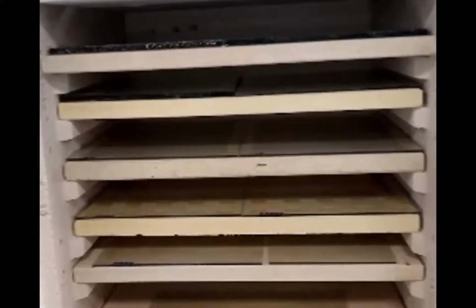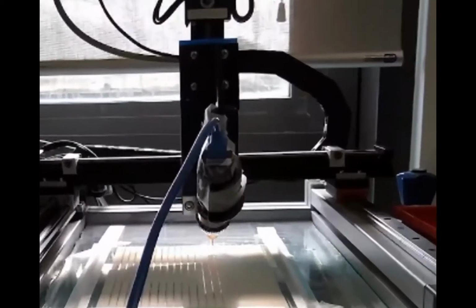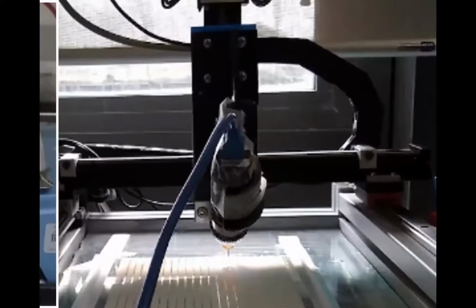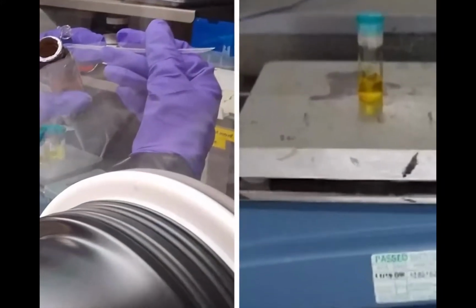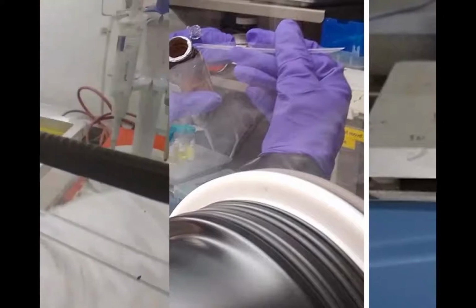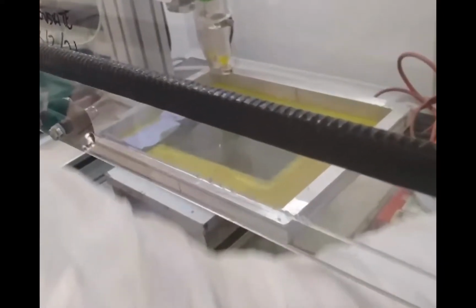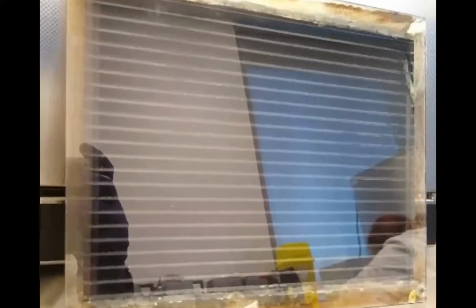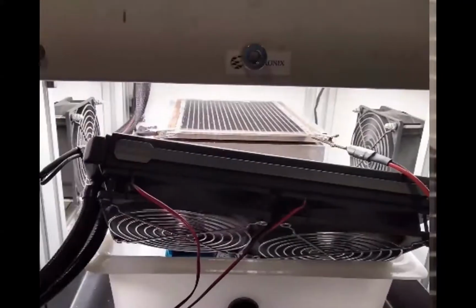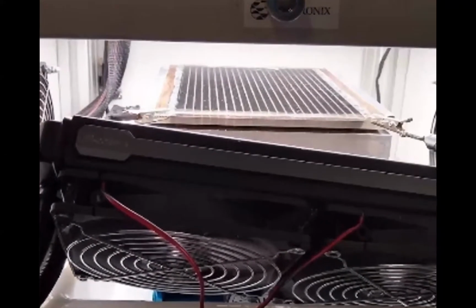Then the coatings are cured in an oven, and any parts of the print that need removing are taken off using scribing. Then the perovskite solution, which is the light harvesting material for the solar cells, is made in a glove box and then heated up. Then this is syringed onto the printed layers and cured in an oven. Once dry, the electrical contacts are soldered onto the sides of the solar modules and the wires are attached. And here we have a finished printed solar module. These can be tested under an incredibly bright light, which is the equivalent of one sun, to see just how well they perform. And then we can encapsulate them and put them on our roofs.